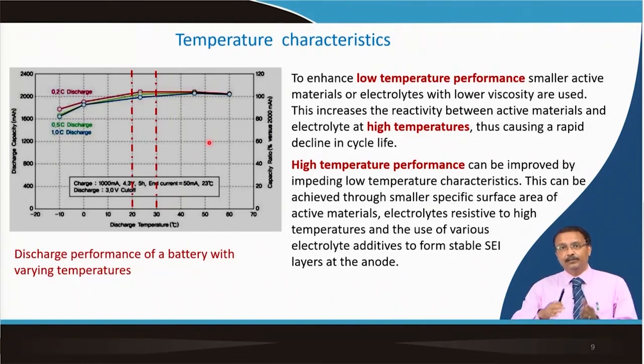The increase in the reactivity between the active material and electrolyte at high temperature is more important because they can react relatively with high vigor. So, that causes a rapid decline in the capacity. So, high temperature performance can be improved by impeding the low temperature characteristics. It is already less viscous, of course. And as I have described, a smaller specific surface area of the active material may be important. So, the particle size is relatively large, the electrolyte is resistive to high temperature, and thus use various electrolyte additives to form a stable SEI layer.